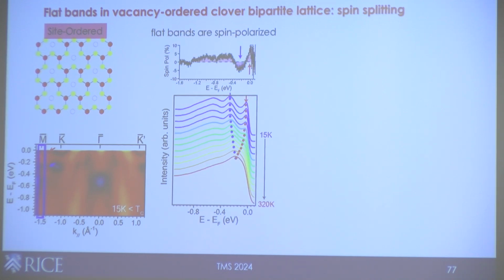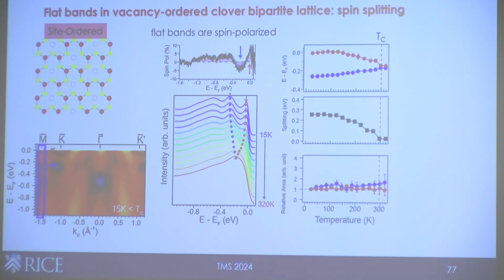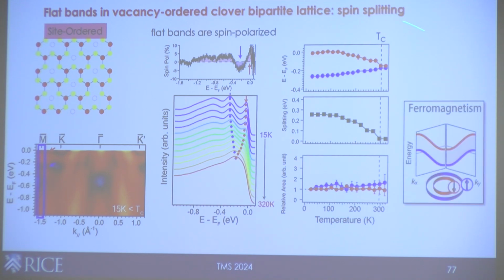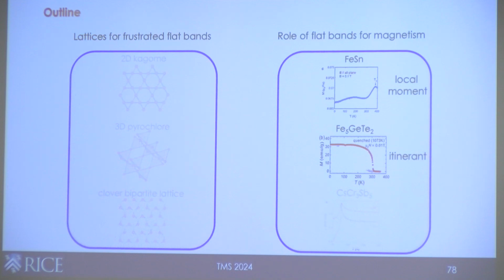And because this is a ferromagnet, we can also look at the spin polarization. We did spin polarized ARPES. You can see that these two flat bands actually have the opposite spin polarization, right? So the picture that emerges is really close to this spin splitting into spin up, spin down bands across the ordering temperature. And this is in contrast to the case of iron tin in the previous example. I think this is the first time, among all these metallic 2D van der Waals ferromagnets, that you can see spin splitting of the bands across the ordering temperature. So this is sort of another limit of this.